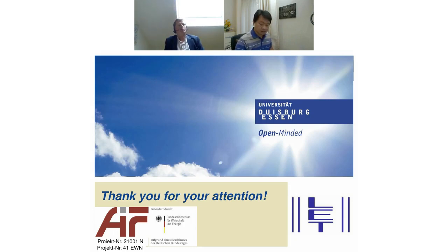Right. So in the one project that I told you about in the summary, we also want to coat the zinc particles with a kind of glass-like coating, which is also quite stable. So the zincate that is forming basically stays inside this coating and can then be electrochemically reduced again upon charging the battery. This is the approach. But of course, there are some issues with the stability of this glass-like coating in strong alkaline media.